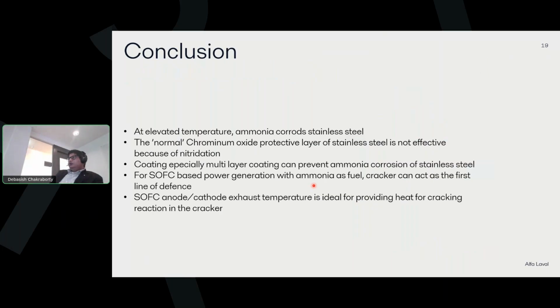So the conclusion is, at elevated temperature, ammonia corrodes stainless steel. It's inevitable. And the normal chromium oxide protective layer of stainless steel is not effective because of nitridation. Coating, especially multi-layer coating, can prevent ammonia corrosion. So you should think about that.